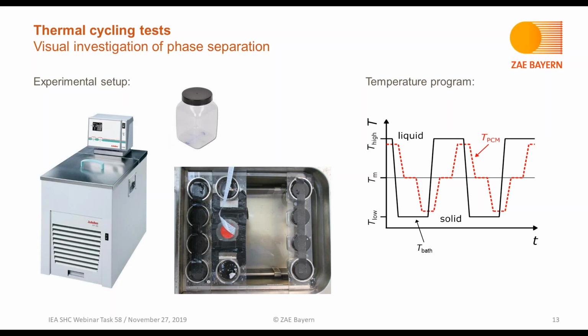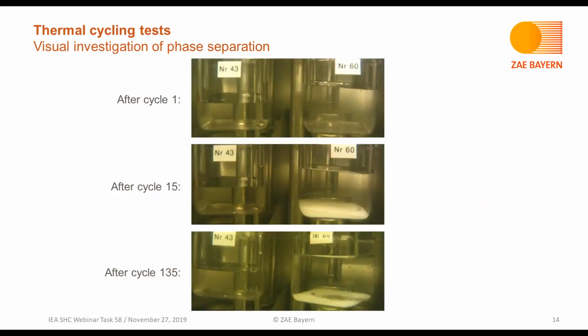What we found out, which is very important and also very useful, is to have a visual investigation of phase separation. Therefore we are measuring the eutectics in such transparent bottles, put them in a thermostatic bath, and then take pictures during the thermal cycles. And this is shown on this slide.